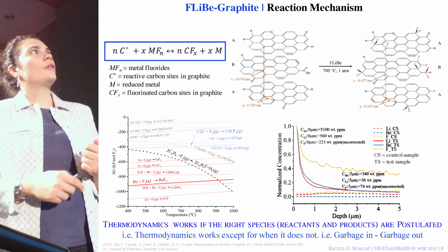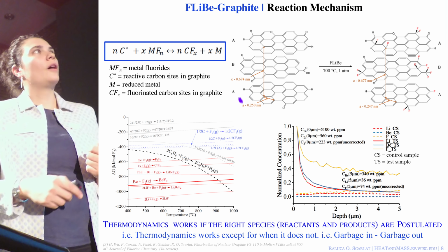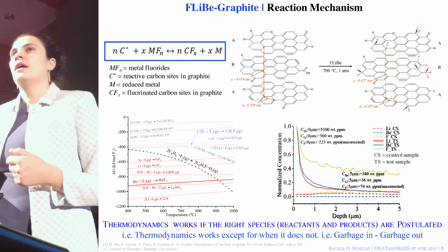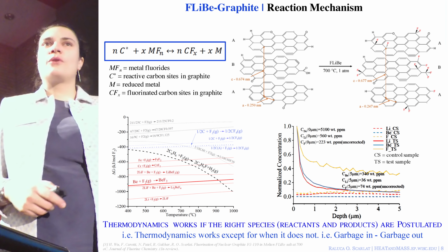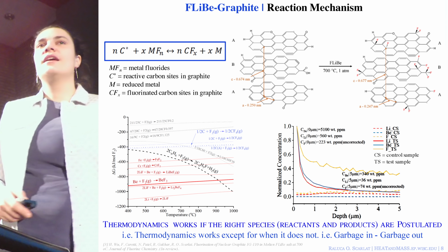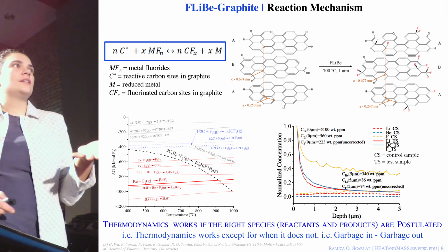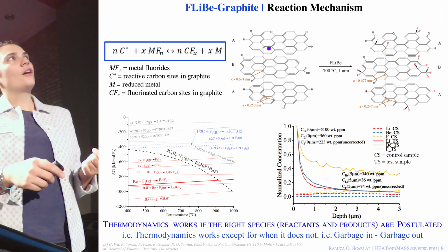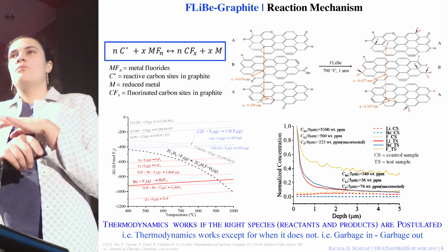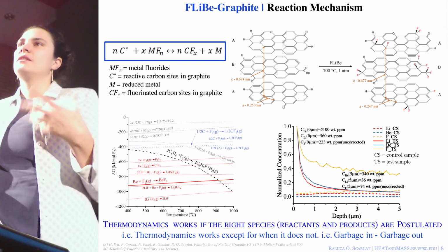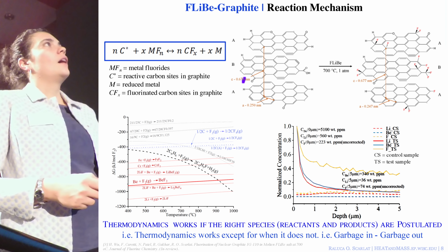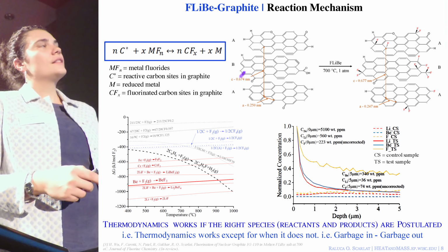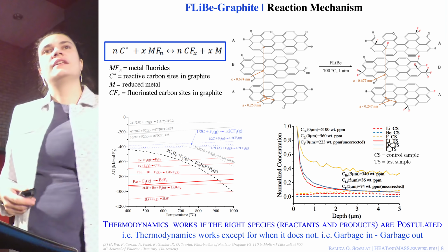Maybe there's a lone pair of electrons, maybe there's a triple bond. And these sites are highly reactive. And so when we look up data for graphite in the literature, that Gibbs free energy data on the Ellingham diagram refers to an average carbon atom far away from any defect in the graphite lattice. But the data for these isolated defect sites, that's not included in the databases.